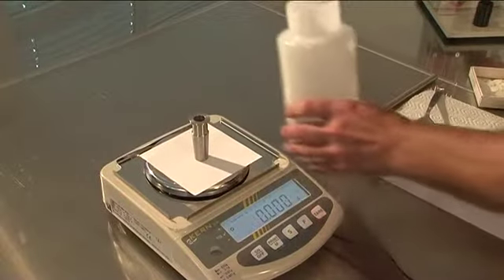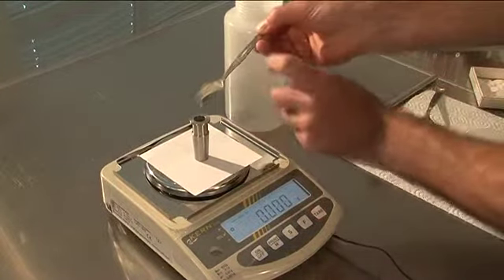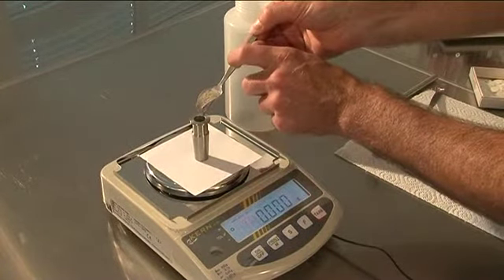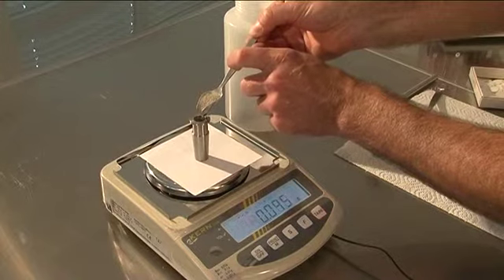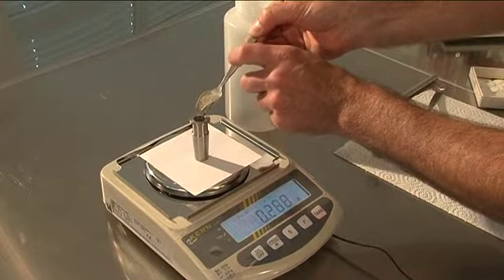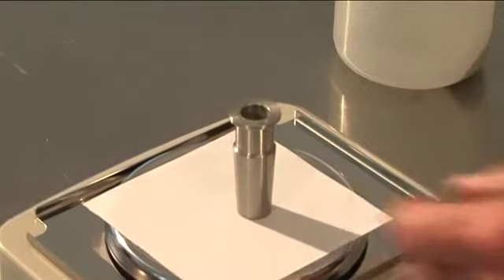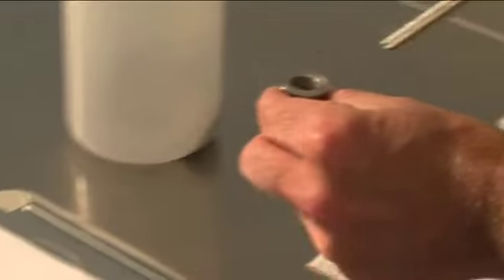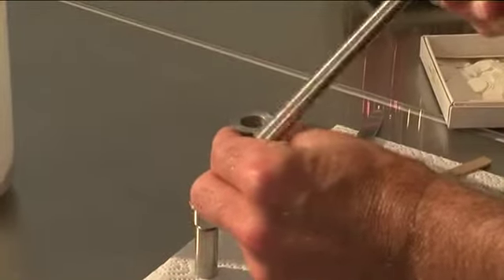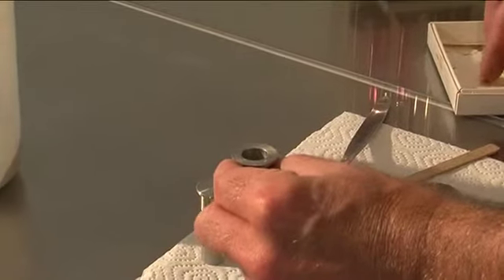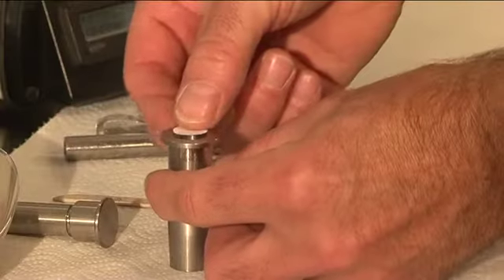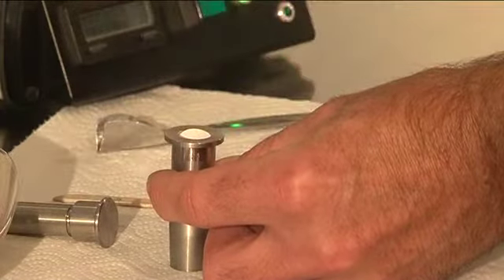The analytical balance is used to accurately weigh out the amount of cement calculated by the computer to 0.001 grams. Different working methods can be applied. Level the cement bed by lightly tapping the exterior wall. Apply another filter disc to the surface area and press it onto the surface with the rod.